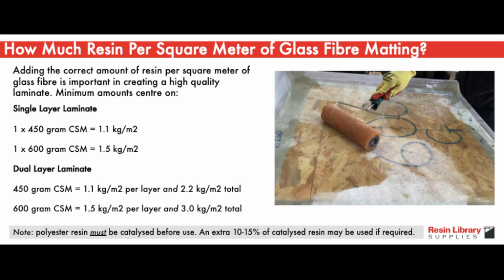Likewise, if you're doing 600 gram matting and 2 layers of that, then you want 1.5 kilograms per square meter per layer and 3 kilograms per square meter in total. You might need an extra 10 to 15% of resin per layer, depending on how the laminate turns out.